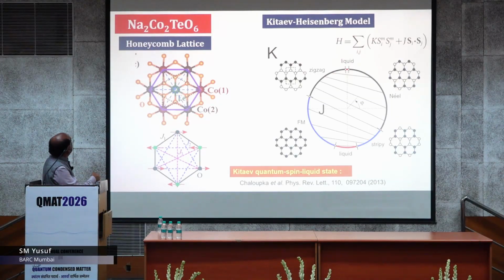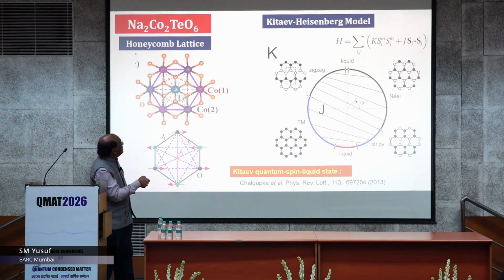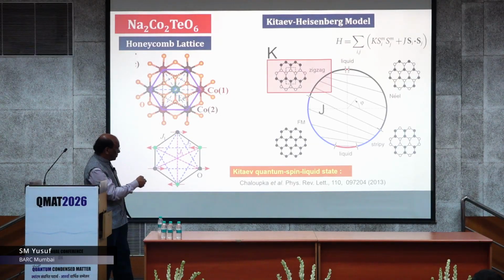This is the honeycomb lattice, where we have shown that both Kitaev and Heisenberg models matter, because as per our neutron diffraction work, this magnetic structure is the zigzag one, and that falls in this phase diagram. See, this is the phase diagram, this is J and this is K. K is the Kitaev term and J is the Heisenberg exchange.